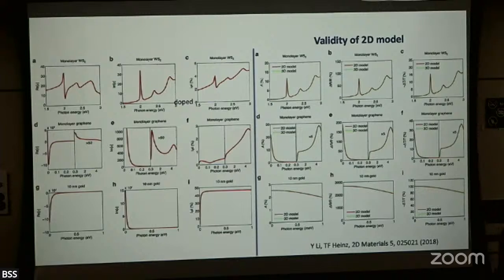Is that the same phi that you had over there? Yeah. But does that depend on D, the thickness? Yes, phi depends on D. So for these materials, like monolayer tungsten sulfide, the first example thickness is about 0.68 nanometer. The second is half of it. And the third one is 10 nanometer.